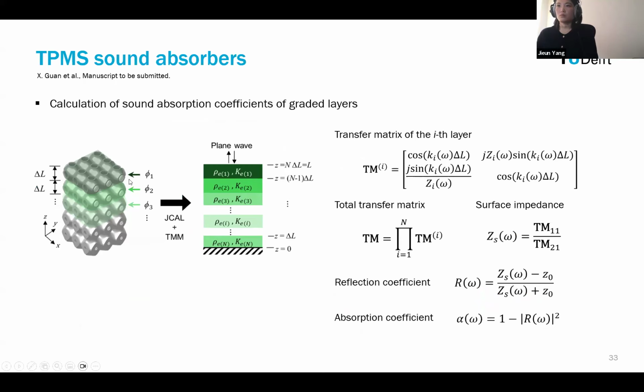And to do that, we also had to make a multi-layer, where each layer has different effective fluid properties determined by the porosity of each layer. And when you have each layer, then the sound absorption coefficient of the whole layer can be obtained by this transfer matrix analysis. So we generate a transfer matrix for each of these layers, and then calculate the total transfer matrix. And by using that, we can obtain the surface impedance. And from that, we can get the reflection coefficient and absorption coefficient.